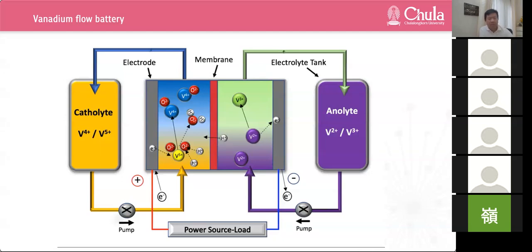Recently, a mixed acid vanadium redox flow battery was reported, in which chloride ions were added to adjust the solvation structure of vanadium ions in the solution, thus increasing the solubility. So the key point is solubility in this case, because our active material is dissolved in the electrolyte. The energy density of the mixed acid vanadium redox flow battery was increased by more than 70% relative to traditional VRB vanadium redox batteries, while expanding the temperature operation window by 80%, by adjusting only the electrolyte, by adding acid.